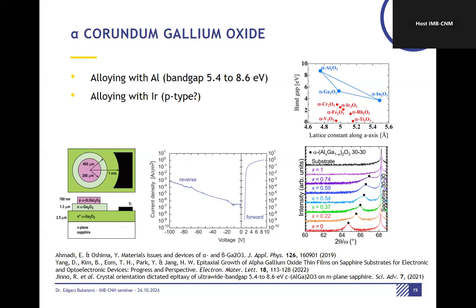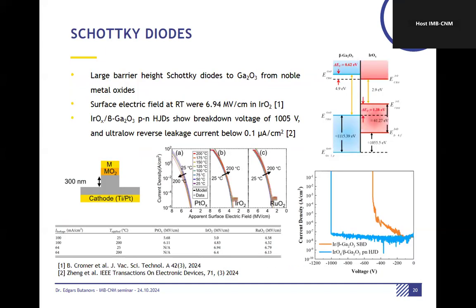So they use this mist CVD. And what is nice, iridium can possibly induce p-type conductivity. That's at least what has been demonstrated. However, the issue is that it's quite an expensive metal, so not many groups work with it. But it could be interesting to explore if possible.